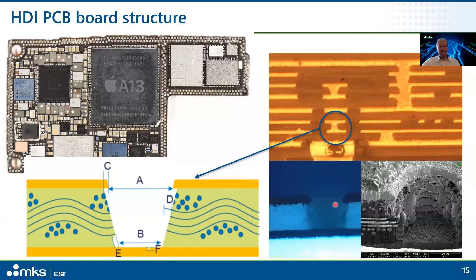Here's an example of how that looks from the side in an SEM picture. That leaves the top copper layer as a challenge, because the mid IR light is also happily reflected there. The key trick is to add a very thin copper oxide layer on top that allows the initial part of the laser pulse to be absorbed, which heats the copper — and warm copper actually absorbs mid IR light reasonably effectively.